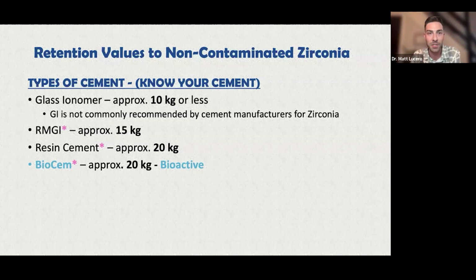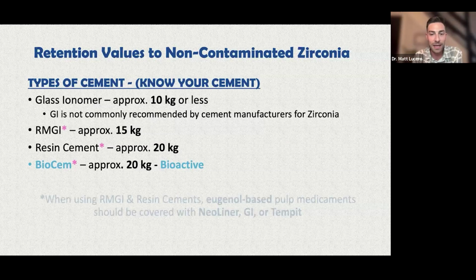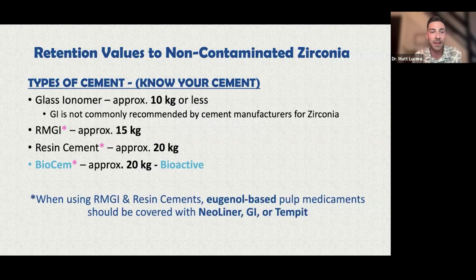So we're not waiting on RMGI to set up for 1 or 2 minutes. One thing to keep in mind with any cement that has resin in it, whether it's an RMGI, an actual resin cement, BioCem falls into this category too because there is a resin component to it, which is why it's light curable. But anytime you're using a cement with resin in it, we have to be cognizant of whether we're using any eugenol-based pulp medicament. ZOE, anything like that, anything that has eugenol, that can affect the polymerization of our cement.